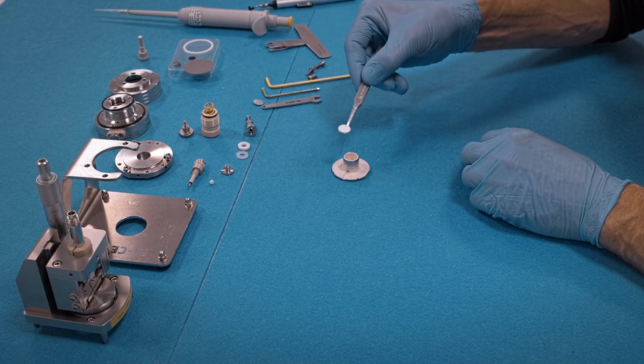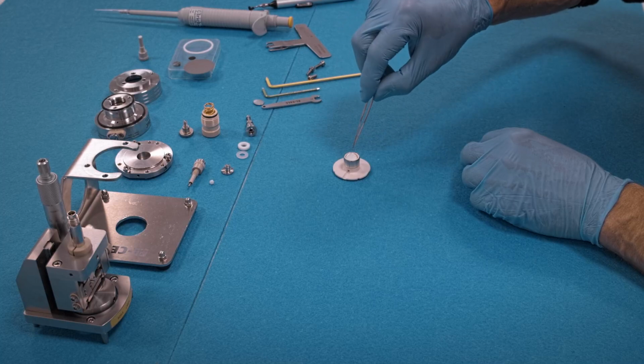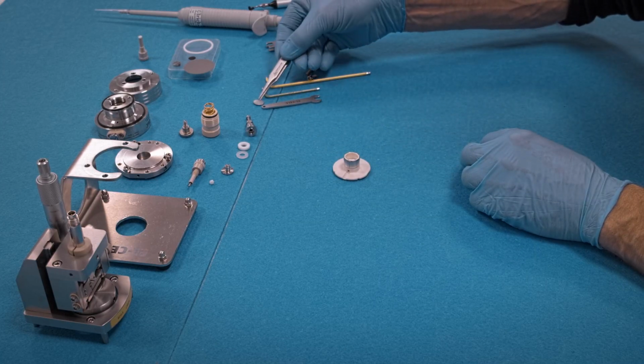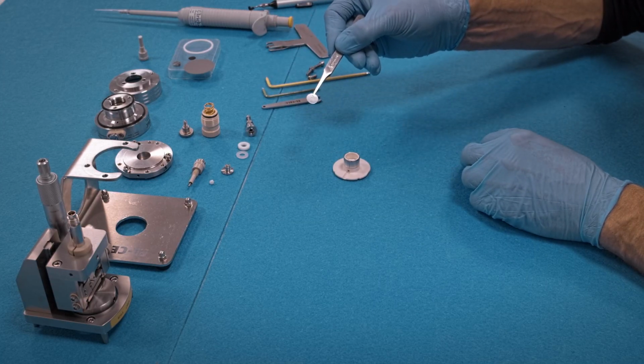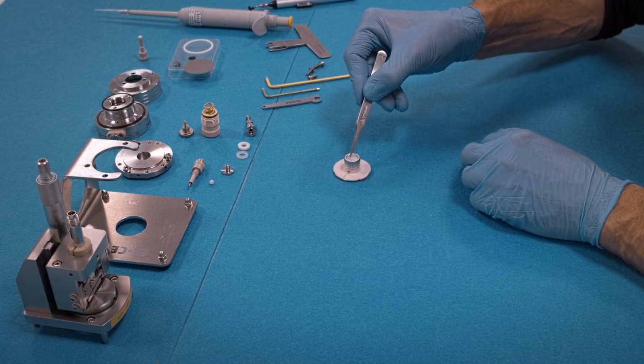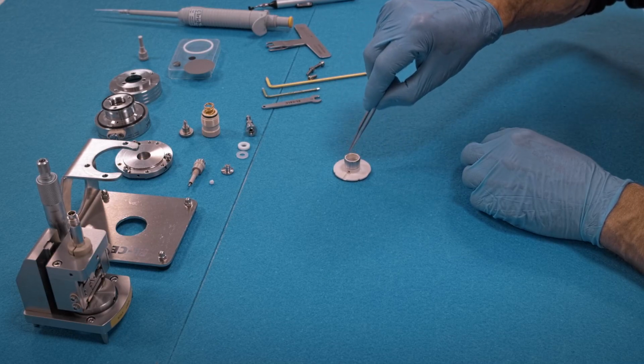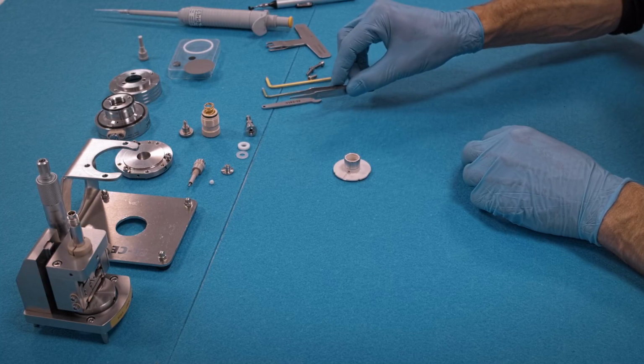Insert the glass fiber separator, 12 mm in diameter, 0.25 mm thick about. Then insert the lithium metal counter electrode, again 12 mm diameter, 0.2 mm thick.